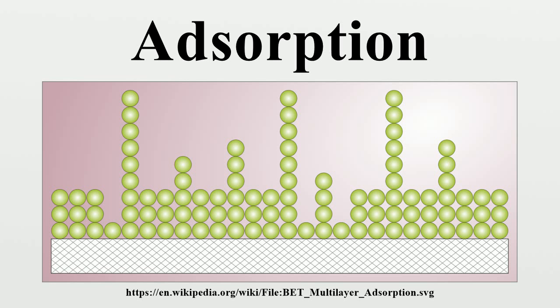Adsorbents. Characteristics and general requirements. Adsorbents are used usually in the form of spherical pellets, rods, moldings, or monoliths with a hydrodynamic radius between 0.25 and 5 mm. They must have high abrasion resistance, high thermal stability, and small pore diameters, which results in higher exposed surface area and hence high capacity for adsorption. The adsorbents must also have a distinct pore structure that enables fast transport of the gaseous vapors.